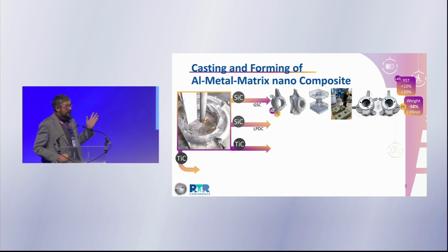We tested silicon carbide by green sand casting, and this led eventually to the production of those components. We managed to use topology optimization and then the modeling of the mold to obtain good performances at lab scale and also at the prototyping scale at component level. This weight reduction refers to the weight of the original steel component to which we had access.